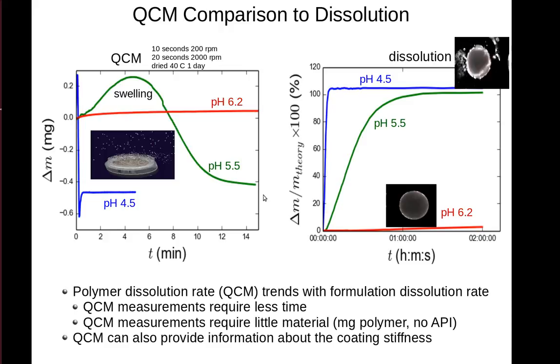This correlates with the traditional dissolution measurement, where we see at a pH of 4 or 5 there's a very rapid release of the API, at a pH of 6.2 a very slow release of the API, and at 5.5 an intermediate release of the API. So again, the two correlate very well.